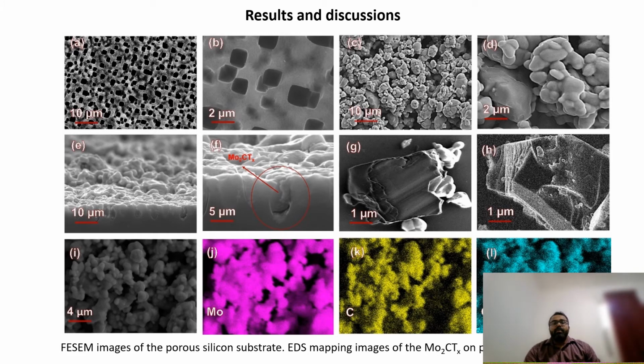Then we took these MXene samples and deposited them on different substrate materials to study the gas sensing performance. First, we used porous silicon substrates. We can see a porous morphology, and the deposited samples showed MXenes decorating the pores. The EDX mapping, that is energy dispersive X-ray studies, also confirms the uniform deposition of MXenes on the porous silicon substrate.